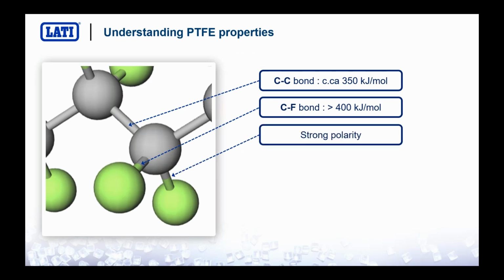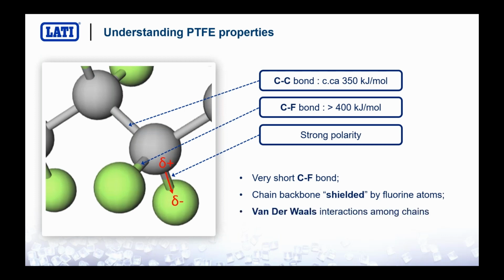It also is extremely polar because fluorine just needs one electron to be perfectly stable, and it takes this electron from the carbon atom, and you have a strongly polar dipole, as we say. What does this mean? This means that you have a very short bond with a very high energy to break it, and this will lead the molecule to be absolutely stable. This means that even if you try, it is extremely difficult to break it. So you have the carbon backbone completely shielded and protected by fluorine atoms, and because of this chemical inertia related to the strong bonds, you have very weak forces that keep the PTFE molecules close to one another.